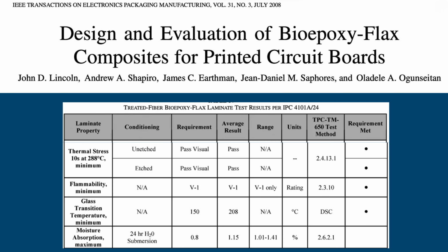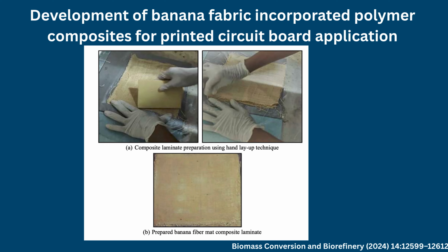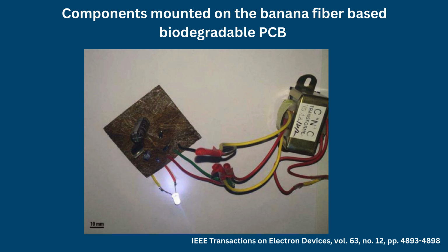Studies comparing jute/epoxy, sisal/epoxy, and hemp/epoxy laminates have reported dielectric constants and flexural strengths approaching those of conventional PCB substrates. Banana fiber wheat gluten composites represent an important milestone toward fully biodegradable PCBs. Although their mechanical properties remain lower than FR4, their density is approximately 50% lower, and they satisfy UL 94 V1 flame retardancy requirements.